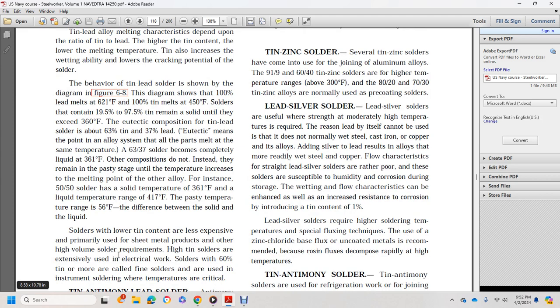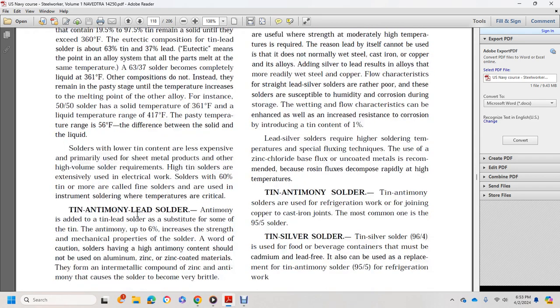For example, 50-50 solder has a solidus temperature of 361 degrees Fahrenheit, a liquidus temperature of 417 degrees Fahrenheit, and a pasty range of 56 degrees Fahrenheit, the difference between solid and liquid. Solders with lower tin content are less expensive and are used primarily for cheap metal products and high-volume solder requirements. Tin solders are extensively used in electrical work. Solders with 60% tin or more, called fine solders, are used in instrument soldering when temperature is critical.